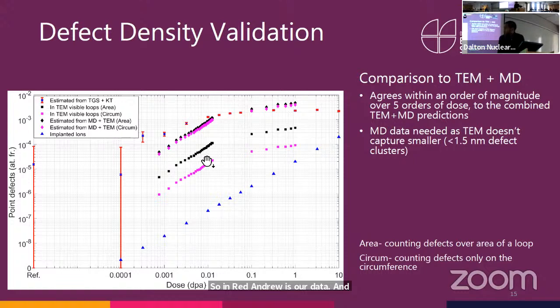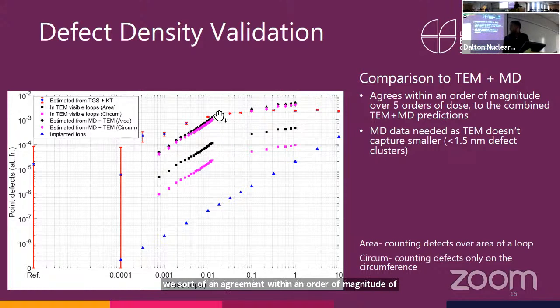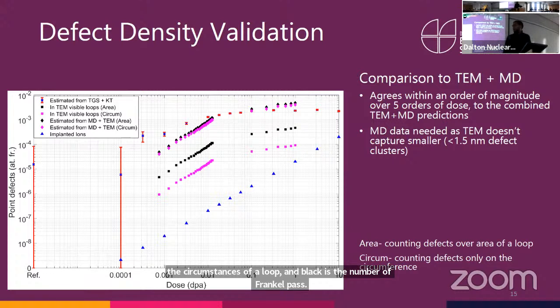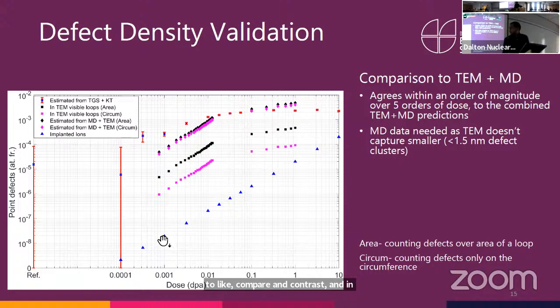So in red and blue is our data, and these square markers are what you get if you consider the TEM defects only. But when you consider the TEM defects with the molecular dynamics predicted defects, then we have an agreement within an order of magnitude over these 5 orders of magnitude in dose, in Frenkel pairs. This showed us the gap between what TEM sees and what TGS is seeing, as well as what TEM with MD would see. Here, purple is if you count defects on the circumference of a loop, and black is the number of Frenkel pairs if you count defects in the entire area of the loop, just to compare and contrast. And the blue triangles are the density of your implanted ions, the ions you put into your material.